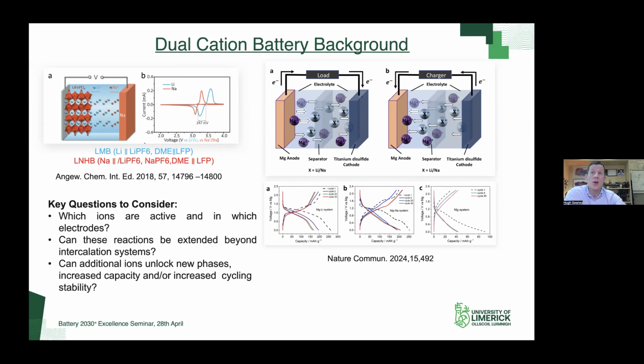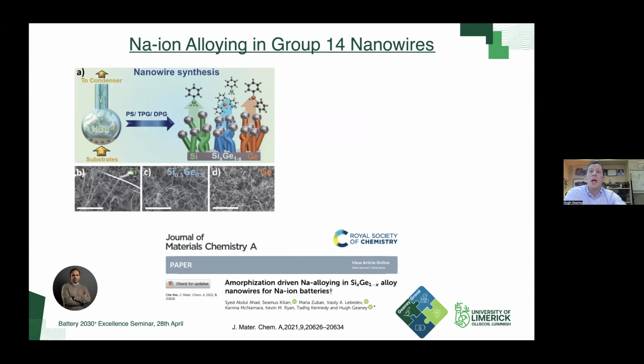If we move to these ternary systems, can we try and unlock new phases and increase the stability? So as one slide of background, this builds on work where we had sodium ion alloying. Again, in these group 14 materials, we investigated different compositions: a germanium scenario, pure silicon, and a silicon germanium 50-50 scenario.